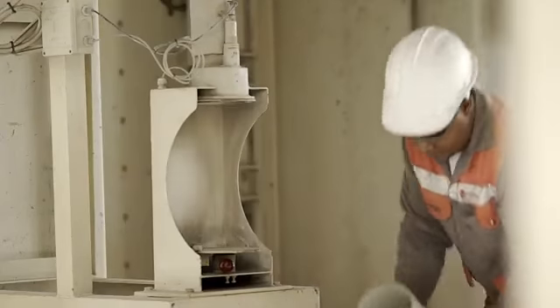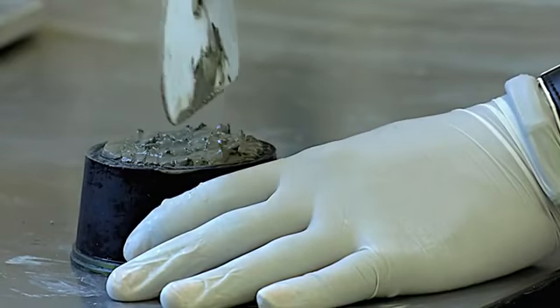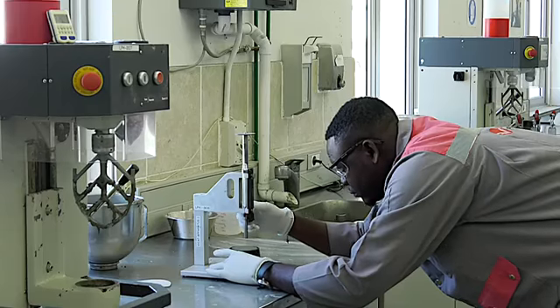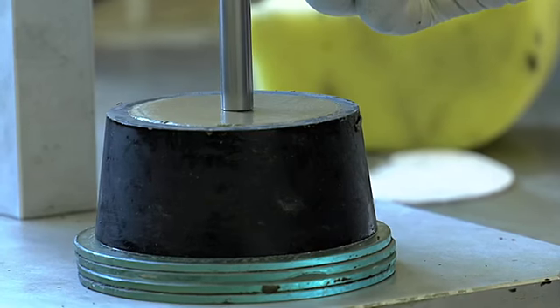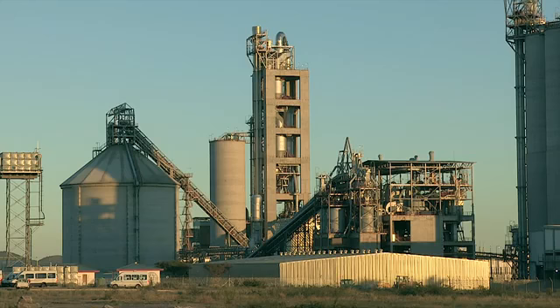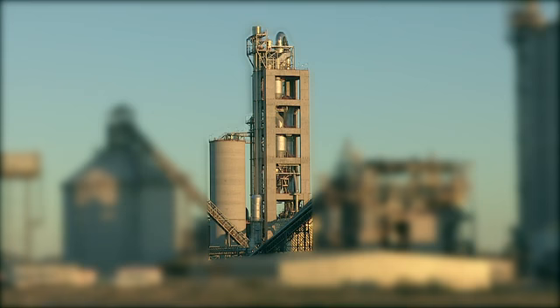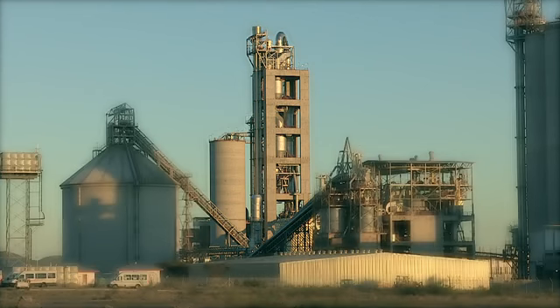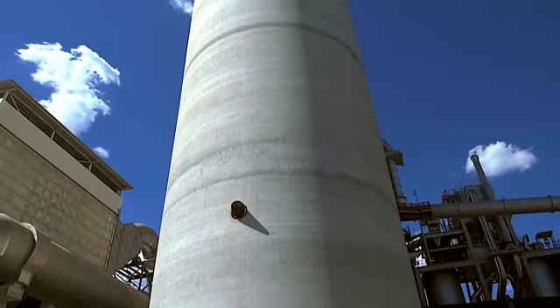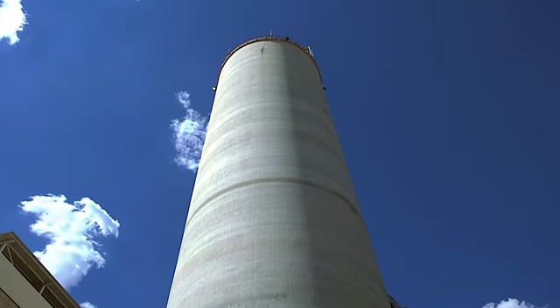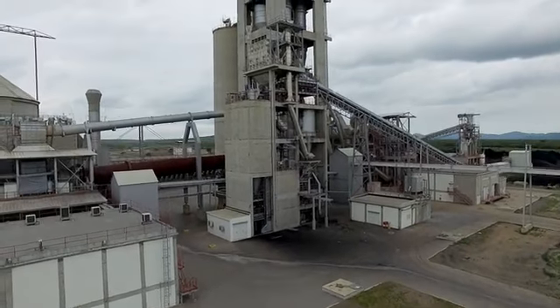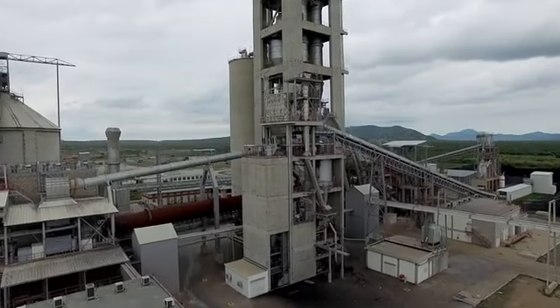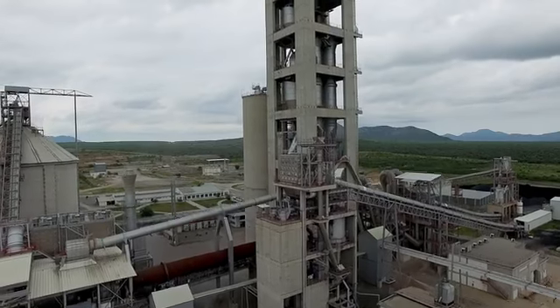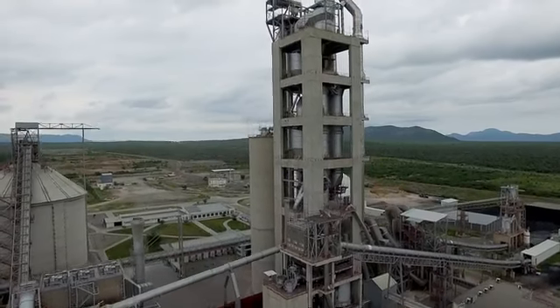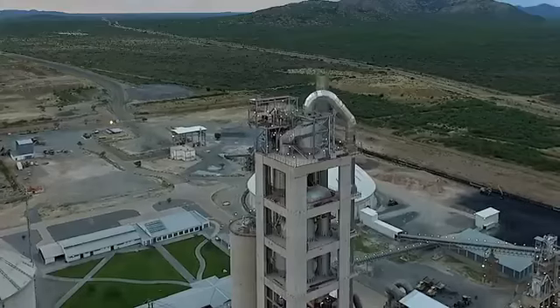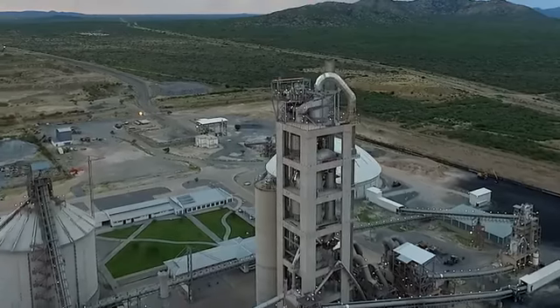The raw meal is tested once again to ensure that the chemical composition is correct in terms of the quality directives. Once the raw meal has passed the tests in the laboratory, it is conveyed to the preheater. The preheater at 109 meters high is one of the highest structures in Namibia. The raw meal silo has a capacity to store 7,000 tons of raw meal powder. The raw meal is preheated and pre-calcined in a state-of-the-art suspension preheater with a calciner before it enters the rotary kiln. The pre-calcination process significantly shortens the actual burning process of transforming raw meal into clinker, saving time and energy.